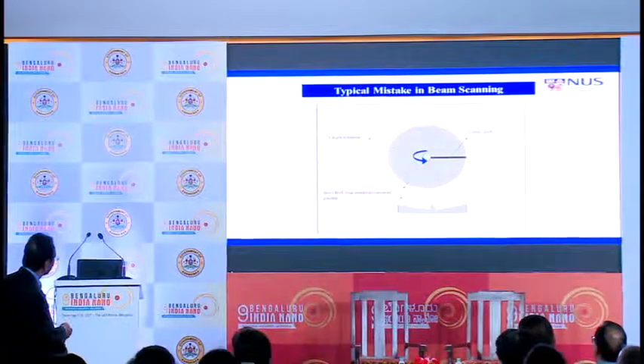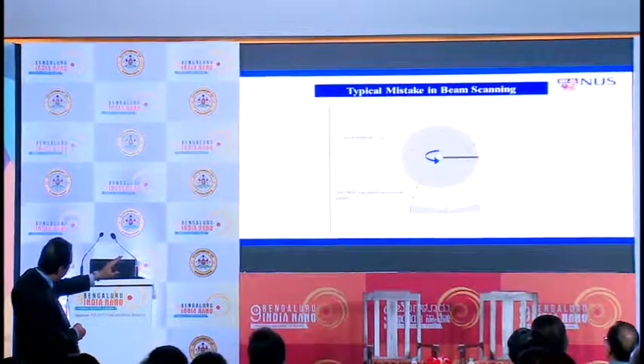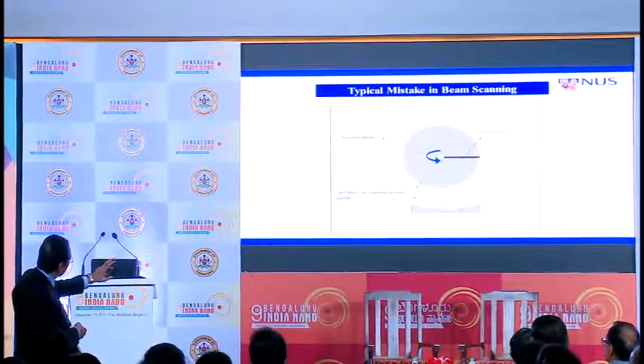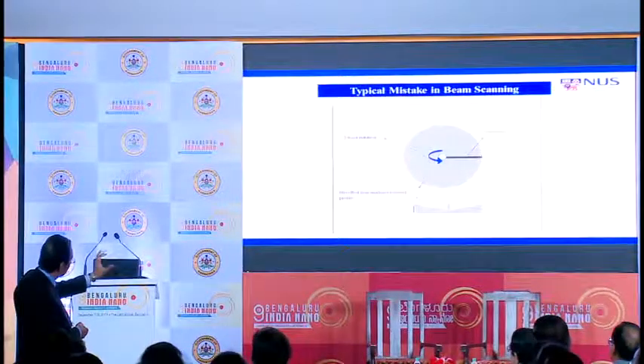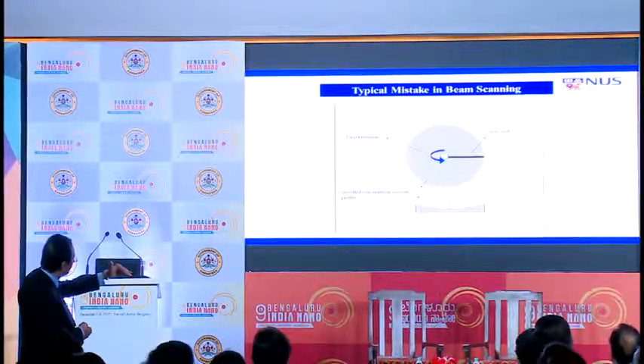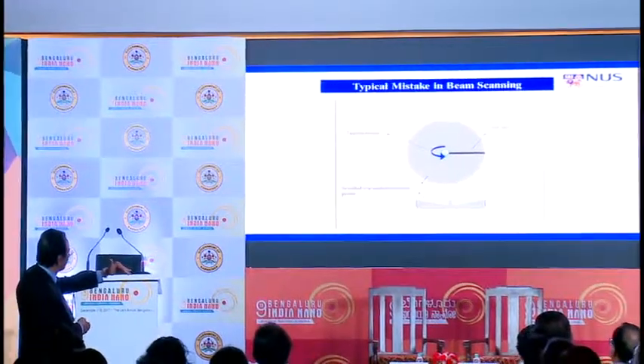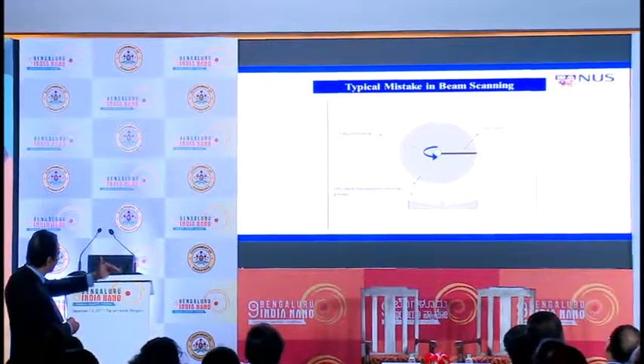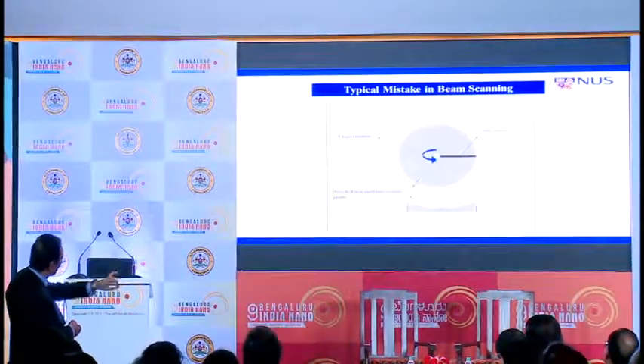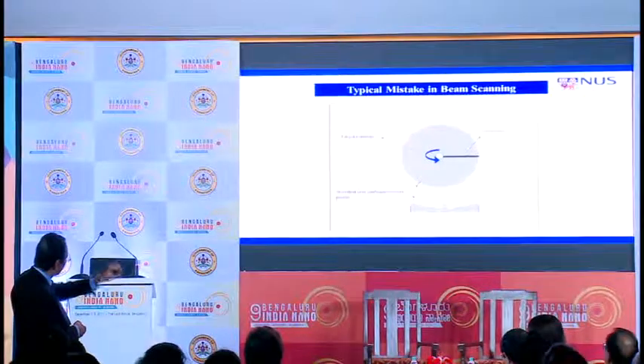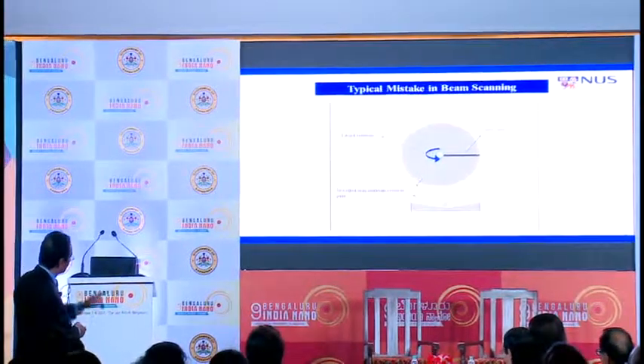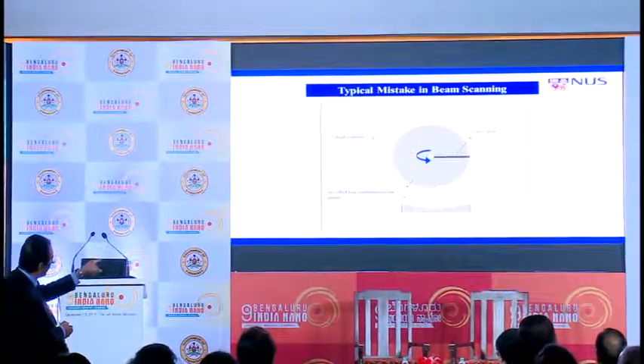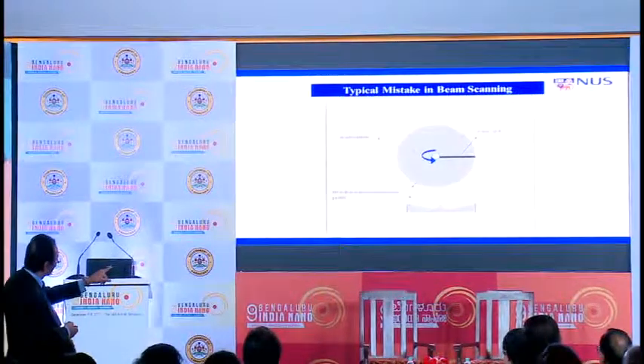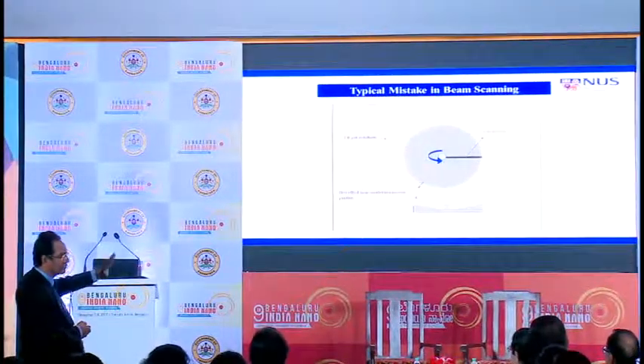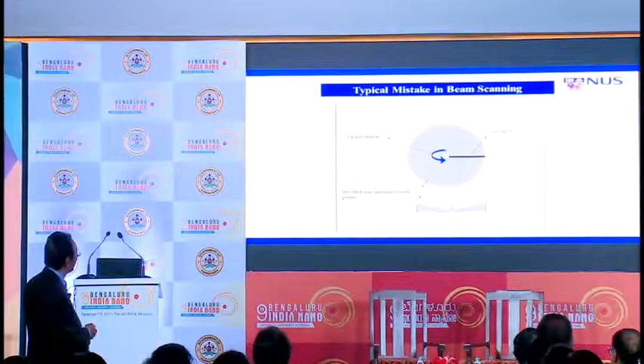One is that at the center of the disk, the laser beam is staying there for a longer time than at the edge, where the linear velocity is larger towards the edge. Therefore, the material etches slowly at the edge, whereas at the center it etches faster. So it develops your target, and the forward-directed component changes angle and goes away from your substrate. So this is a big problem.